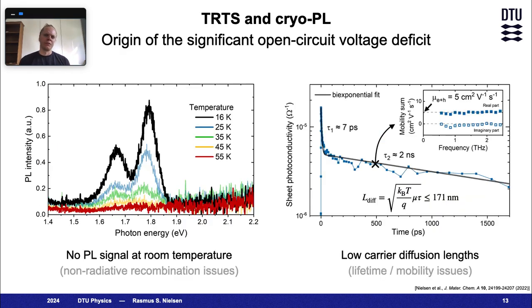Returning to the open circuit voltage deficit, it's clearly reflected from the lack of photoluminescence at room temperature that we have a very severe non-radiative recombination problem. At cryogenic temperatures, we do see two peaks emerge, but at lower energies than that of the band gap, and we have yet to figure out what exactly these radiative emission bands are a fingerprint of.